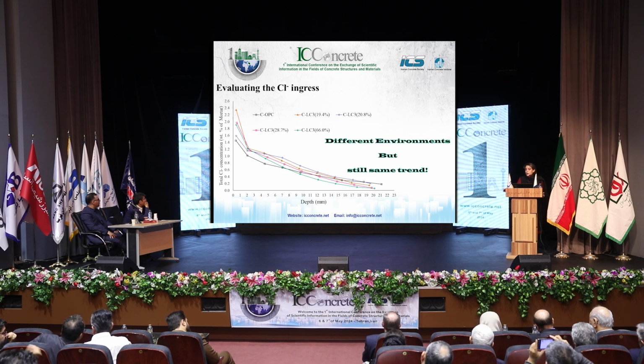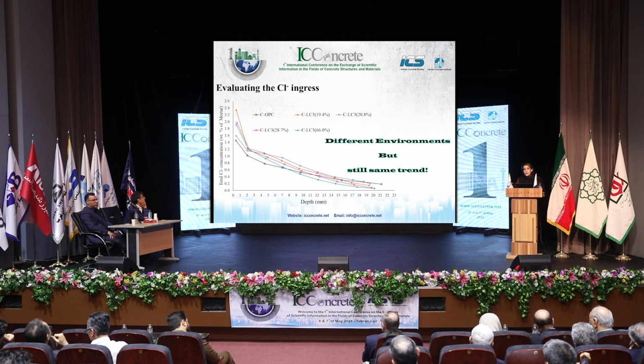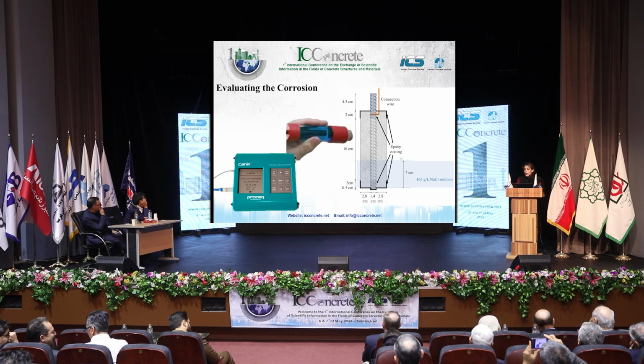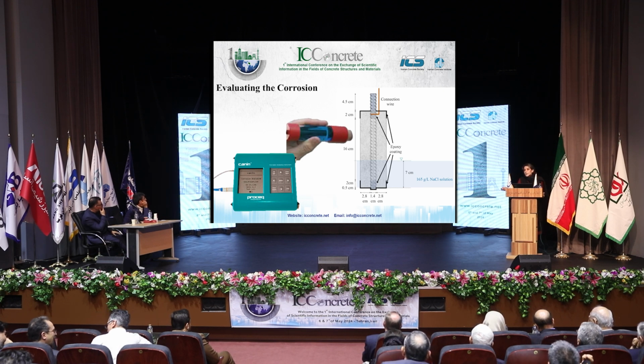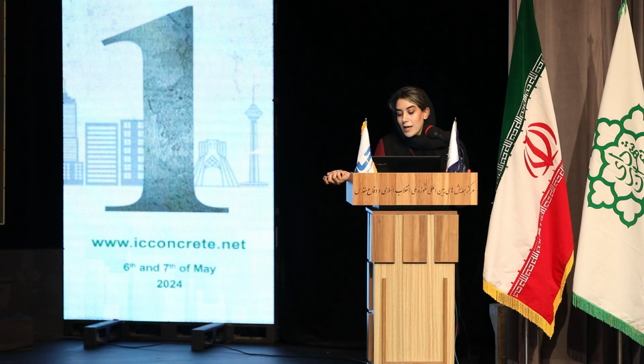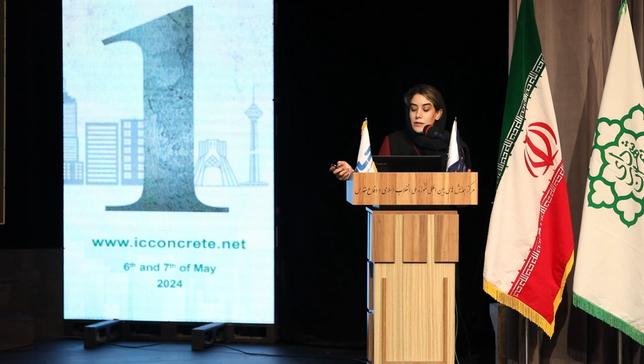But you can see that the same trend happened. It means that at the interior point for LC3 and calcined clay containing binders, we have lower chloride concentration and better behavior. We also evaluated the corrosion in a semi-submerged sample, you can see here, by a half-cell test.